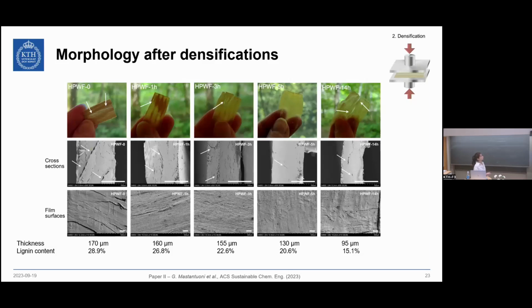And at the same time, we were achieving smoother and smoother surfaces. However, if we push the sulfonation for too long, then we can see cracks appearing again both at the macro as well as the micro scale. And the reason for this is that the lignin that remains in the structure is not sufficient to act as a binder for the whole material.